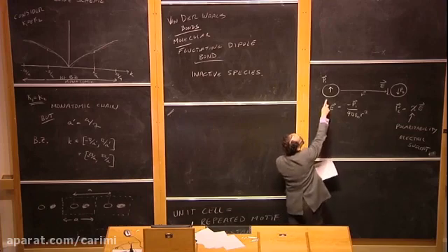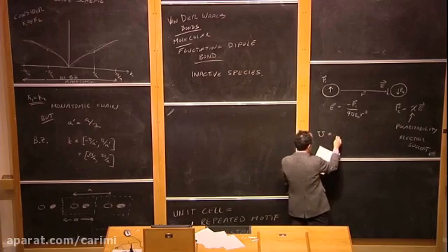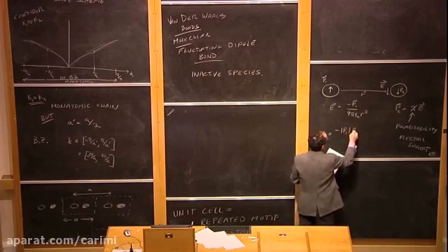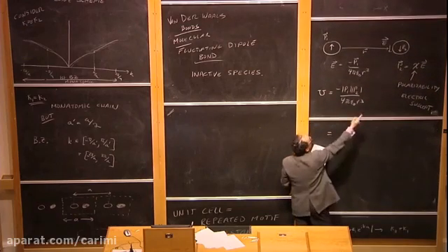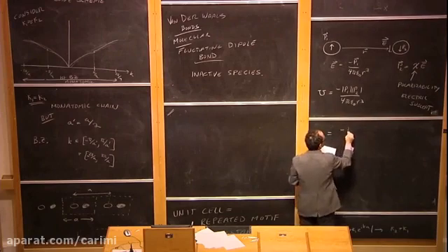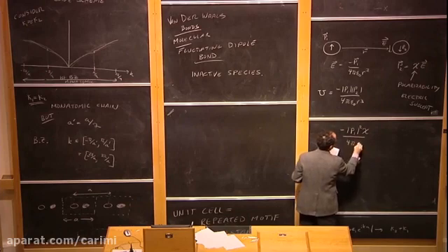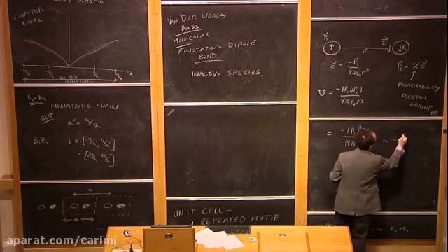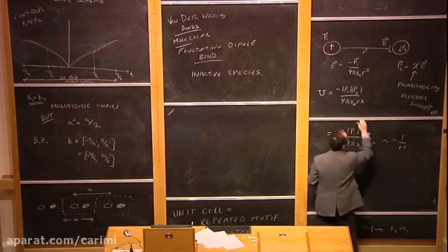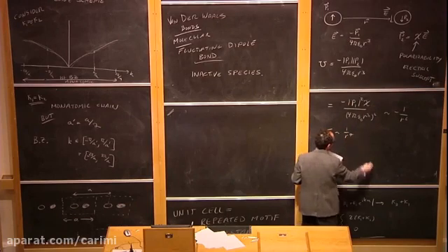Anyway, now what we have is two dipole moments. And you'll remember that the energy of two dipole moments is minus P1 P2 over 4 pi epsilon naught r cubed. So the total energy is then, just plugging these things all together, minus P1 squared chi over 4 pi epsilon naught r cubed, all squared. And in particular, this is negative and goes as 1 over r to the 6th. So the force goes as 1 over r to the 7th.